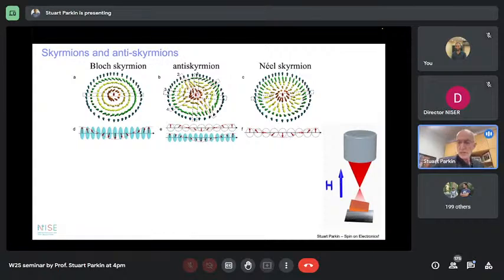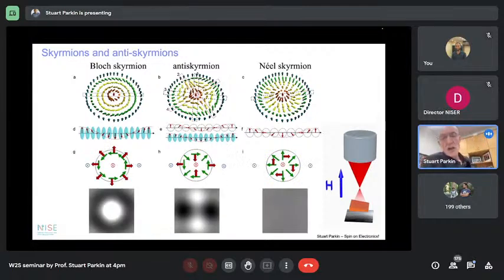So this electron beam can pass through it, and we detect the beam on the other side of this specimen, and then because of Lorentz forces, the beam will be rotated. And in the case of a Bloch skyrmion, the beam, because of the nature of that domain wall I mentioned, the Lorentz forces cause the electron beam to be focused in the middle of the object, and you will see a bright white spot, as shown on the bottom left.